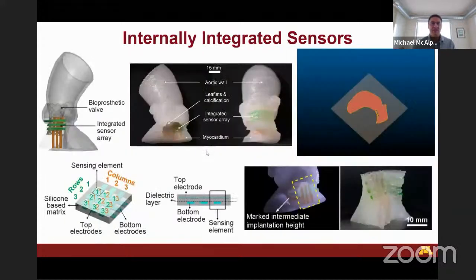And once again, we incorporated some of these ionic hydrogel sensors into the model, but this time, instead of being printed separately and then pasted onto the model like we did with the prostate, we're at a point where we can integrate these devices. So this is a 3x3 array, 9 of these sensors fully integrated into the model. And you can see here that it's built up. Those are the 3 dots on the right-hand side. As we build the model, we can build these ionic hydrogel electrodes directly into the model.